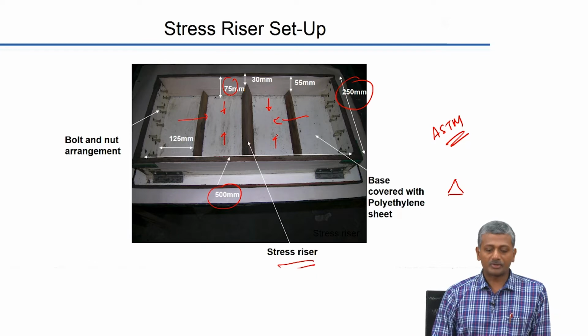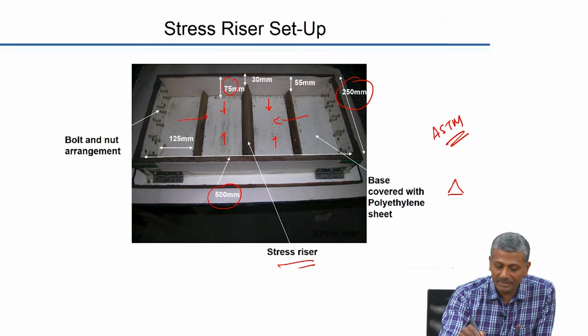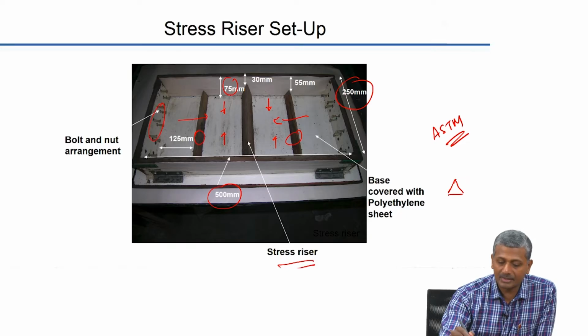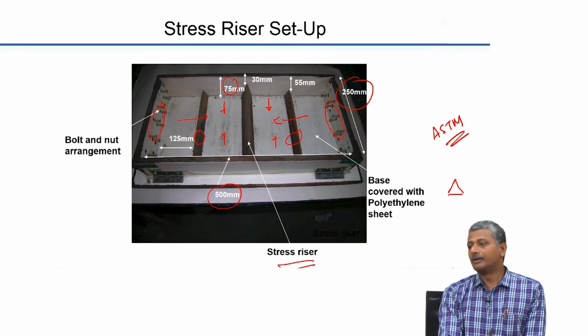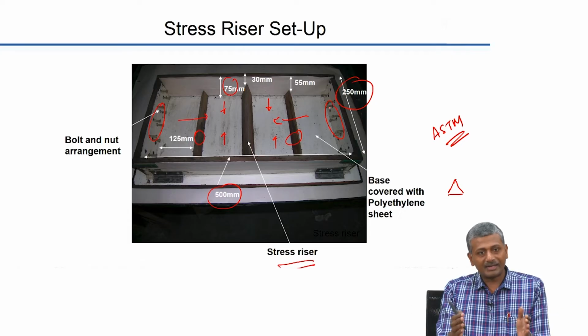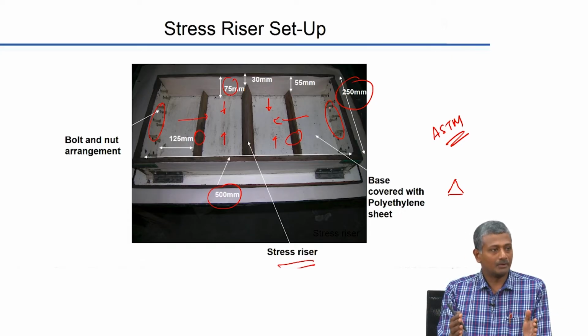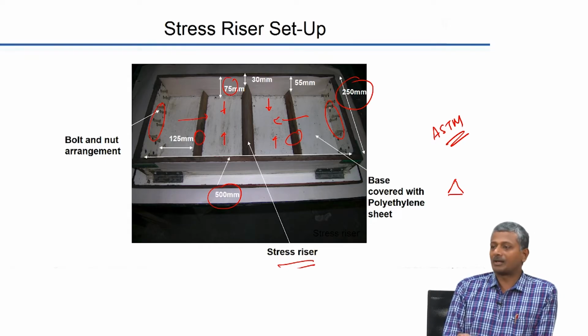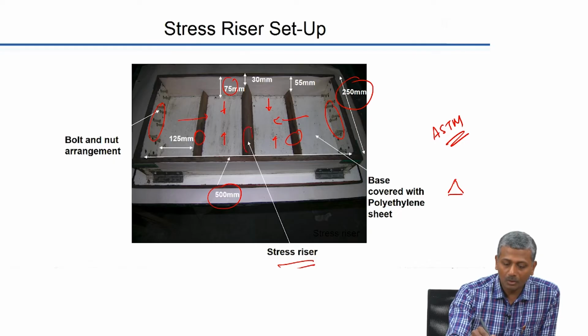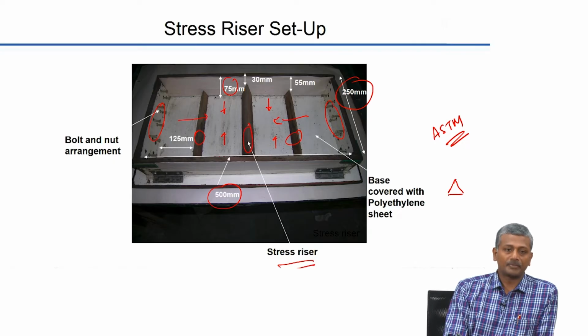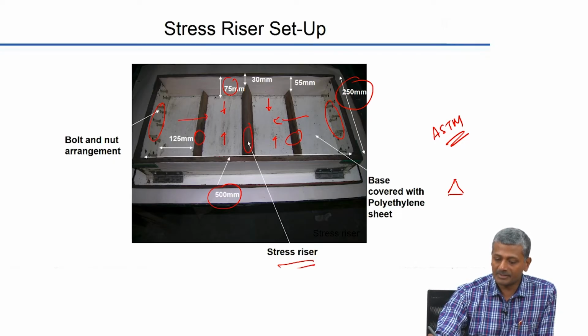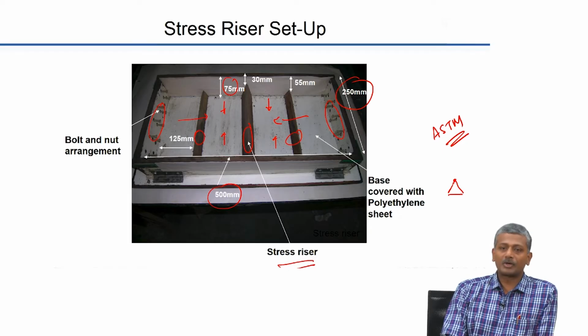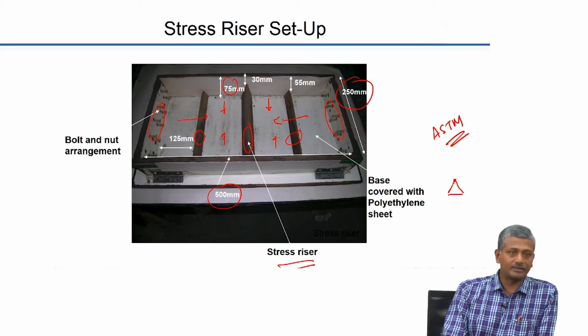Okay. Now, because of the restraint offered by these additional wedges that are provided here and the bolts and nuts that are provided at the ends, the movement of concrete inside is going to be restrained. Once you do that, concrete has to crack, and the most probable location where cracking will happen will be right on top of the stress riser. Why? Because we already have a stress concentration at the tip there, and because of that the crack has to originate exactly at that location.